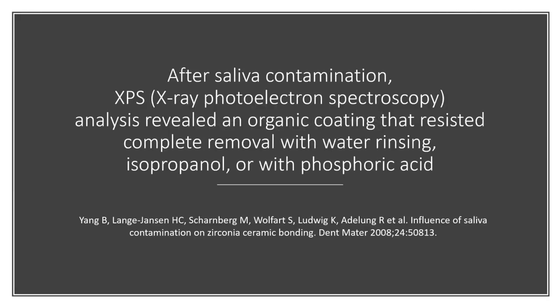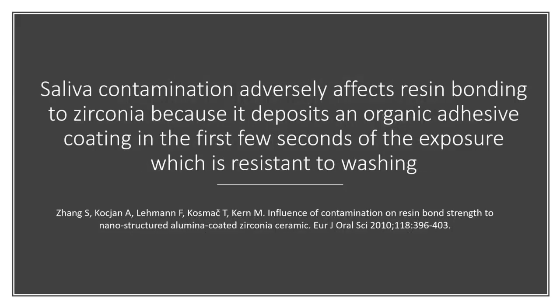You try in your crown and you have saliva contaminate the inside of the crown. And an XPS analysis shows that you have this organic coating that basically resists complete removal with water, alcohol, or phosphoric acid. And most dentists think, I'll just rinse it with water or alcohol and it's clean. Studies show it's absolutely, positively not. And the worst thing you can do with zirconia is phosphoric etch it. It's the worst thing. So saliva contamination adversely affects resin bonding to zirconia because it deposits that organic adhesive coating in the first few seconds of exposure. So people say, I'll just do it quickly and wash it off. Study after study says no.